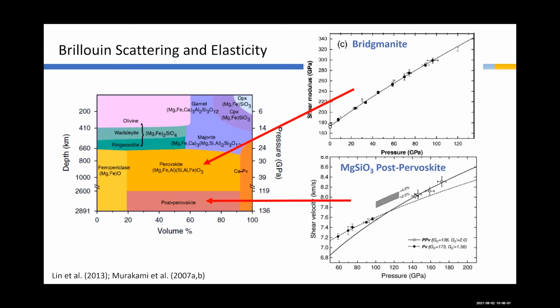So my most recent work, our group, we try to use Brillouin scattering to obtain the combined effect of pressure and temperature on the elasticity of mantle minerals. When we look at most of the previous work, it was performed at either high pressure at 300 Kelvin or high temperature but 1 bar. That means when we try to use those experimental results to model the sound velocity of mantle minerals, we have to extrapolate these high pressure or high temperature results.